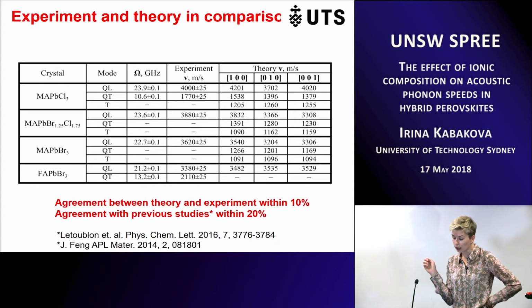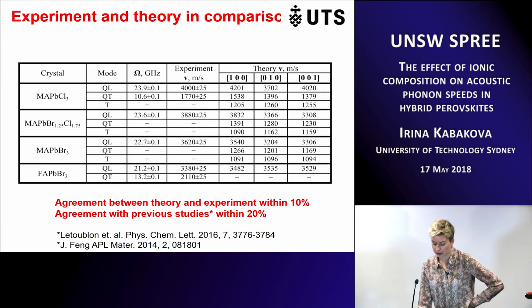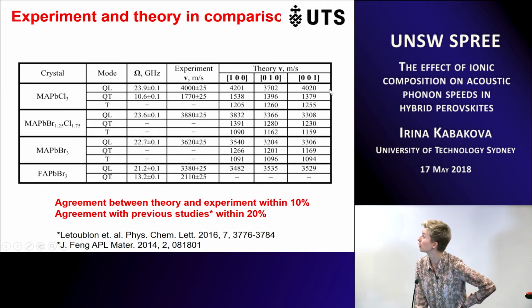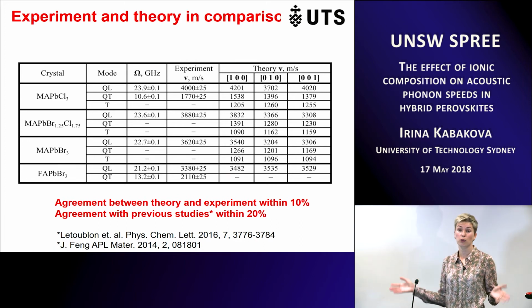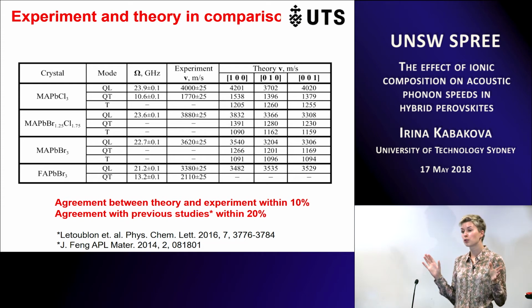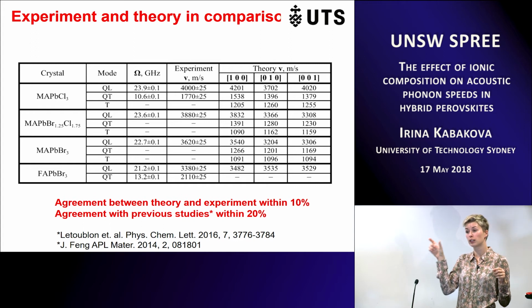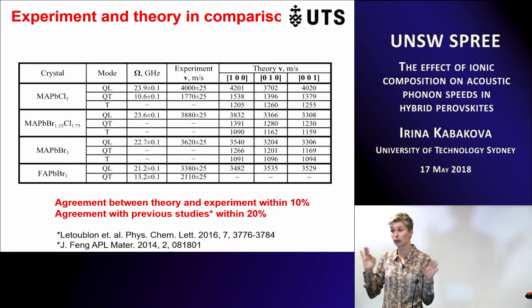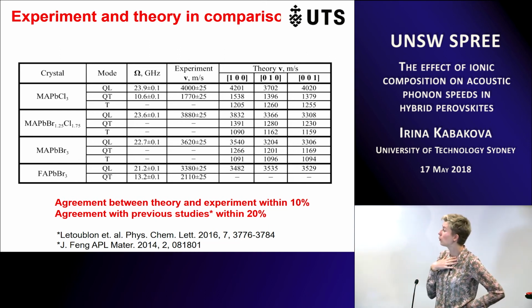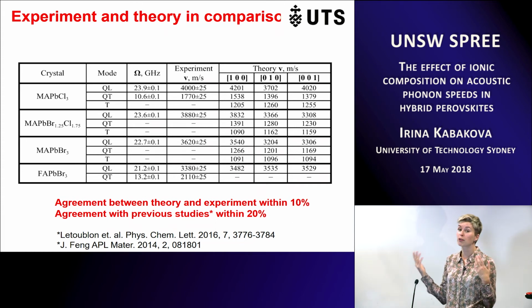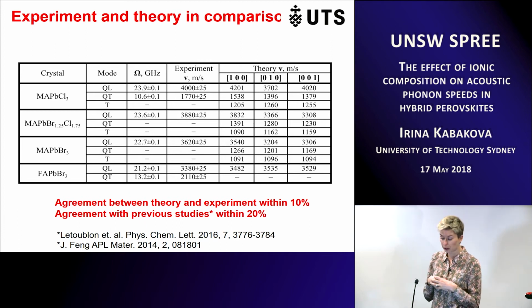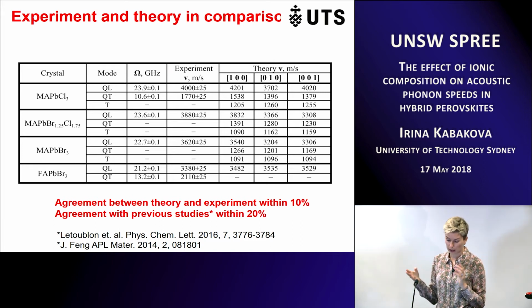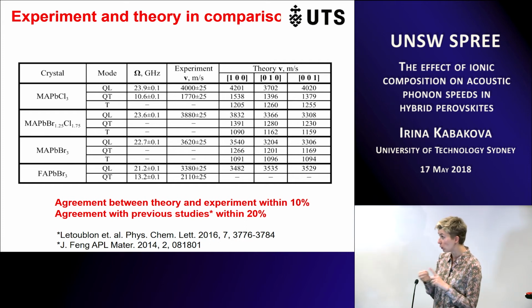David and Ido, who did the calculations in Israel, were very careful and ran calculations for different directions along three principal axes. What you see here is that the numbers are different, and I mentioned that if it's a pure cubic system, then the numbers should be the same. But in fact, it was very hard to do a realistic calculation, so they had to do an approximation and fix the orientation of the cation molecule. So the organic molecule orientation was fixed, and therefore the cubic symmetry is broken and the speeds are slightly different. But what we can see is that the agreement between theory and experiment was actually pretty good. We were surprised how close the numbers came together, and we got fairly good agreement with the published literature on the same crystals obtained by AFM nano-indentation measurements and by Brillouin measurements as well.